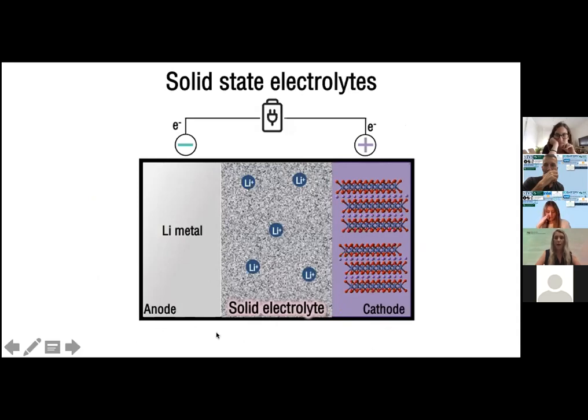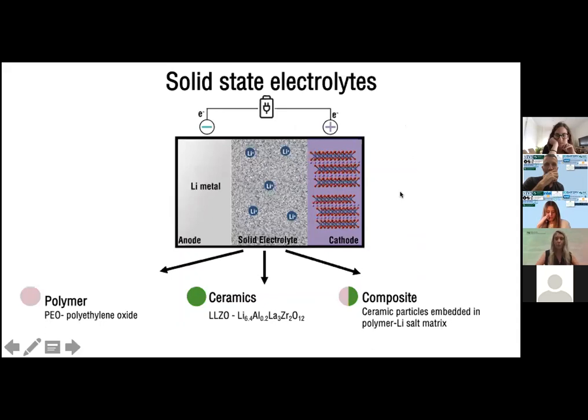And one of the ways to do that is to switch your liquid electrolyte to a solid state electrolyte. There are a lot of families of solid electrolytes. These are only three of them. You have the polymer one, which basically uses polyethylene oxide. You have the crystalline one that is based on ceramics, and one of the promising ones is LLZO, lithium, aluminum, lanthanum, zirconium oxide. And the combination of both is ceramic particles embedded in a polymer lithium matrix. So I will today concentrate on the composite structure.